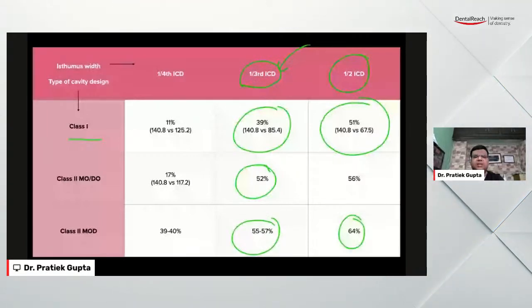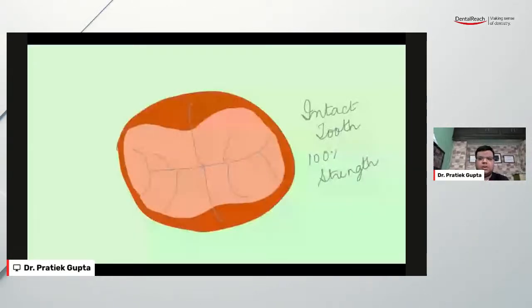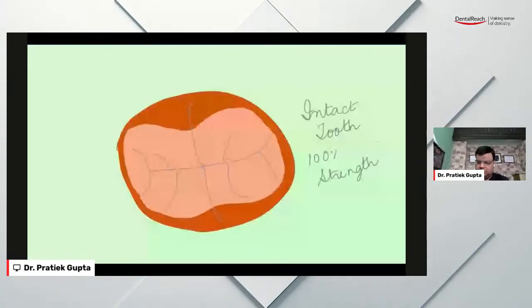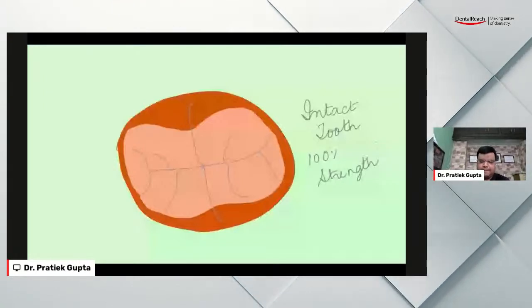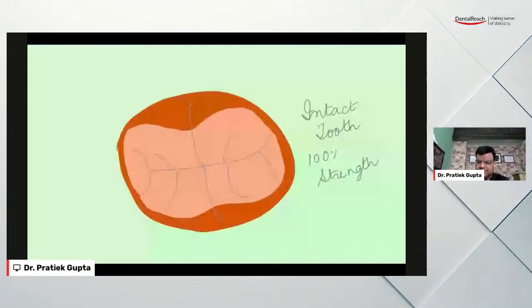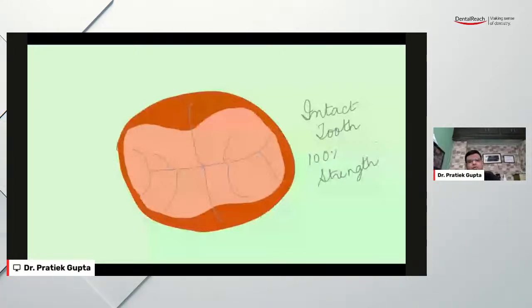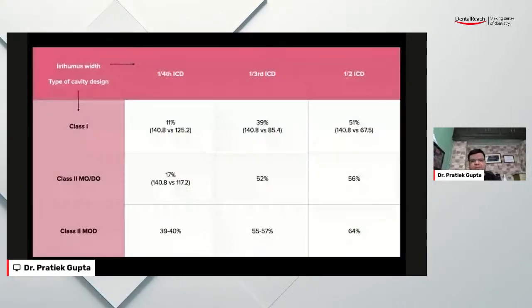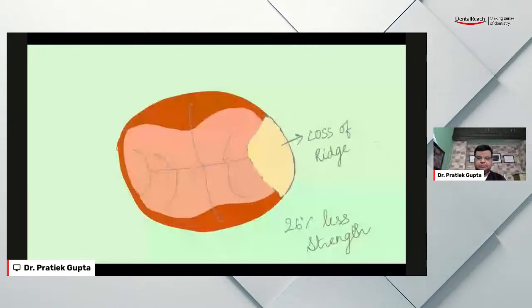What's the point in doing a restoration if it cannot come back to its original function? If you are ultimately going to lose that tooth, when you have 100% of the strength when it is intact, you lose about, sorry, that's an animation that doesn't play here. So you lose about 30% of its strength or 40% of its strength when you just do an MO, and you lose about 70% of its strength when it becomes an MOD. There's no point in doing a restoration because eventually it is going to fail.